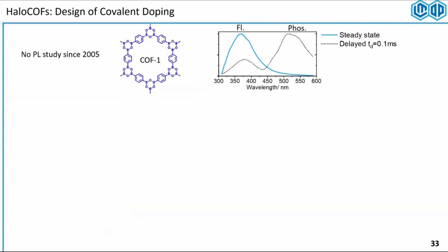But I had a lot of COF1, this phenylene diboronic acid condensation, because I used it for my model compound reactions to do the transesterifications, if you remember. I had a bunch of it laying on the bench. I thought, let's see what sort of luminescence this compound has. Surprisingly, no one studied the luminescence of this COF. It's the first COF reported in 2005 by Omar Yaghi in a Science paper. And after 20 years, no one looked at this luminescence, which was very surprising. It looked like a very luminescent COF.